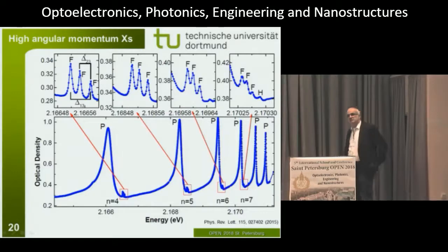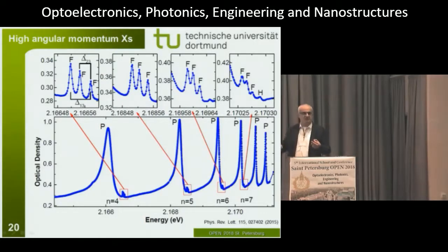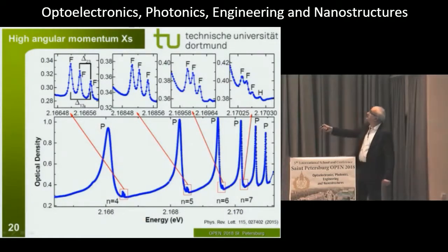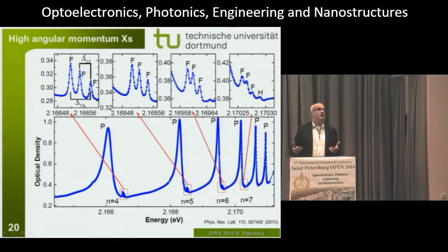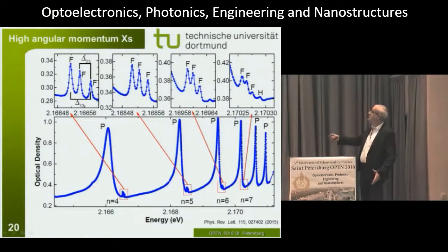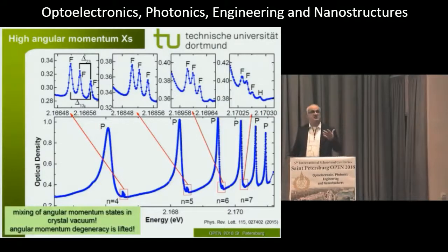This tells you already that what you know from hydrogen, degeneracy of angular momentum states, is no longer true in the crystal. Moreover, the F excitons are split, which tells you also that angular momentum is not a good quantum number anymore. And this is also the reason why we observe these states. Because angular momentum is not a good quantum number in a crystal, these angular momentum states become mixed, and some oscillator strength is transferred from the P excitons to the F excitons such that we can observe them. So clearly there are differences from the simple exciton description that you learn in solid state physics. Yeah, the hydrogen model is not in all cases sufficient.